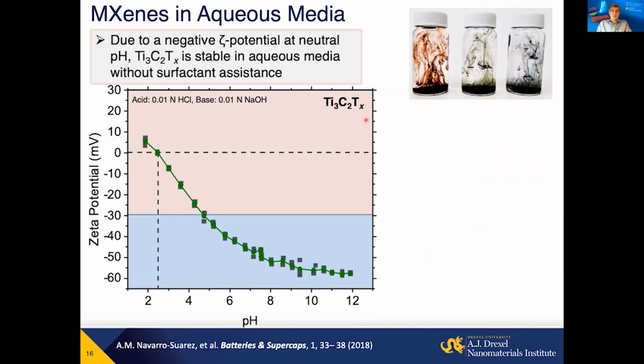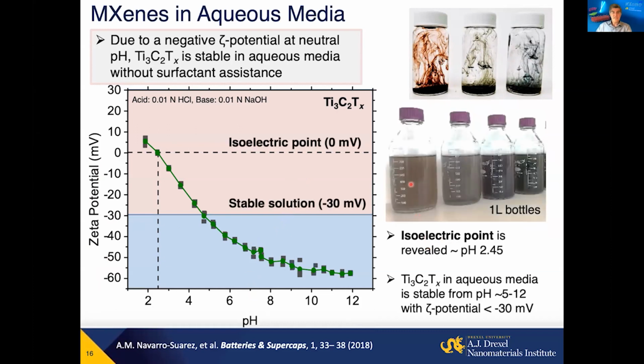So why can we dissolve it so fairly easily? Because MXenes have high specific surface charge on the surface. Zeta potential in solution is typically between -40 and -80 millivolts. So this is a repulsion of particles in solutions. And you can see several different MXenes, you can judge by different colors, being dissolved in water when a droplet of concentrated solution is dropped into water here. And naturally, then we can produce a dilute solution of single layer flakes. Those are 1 liter bottles of MXene flake solutions.